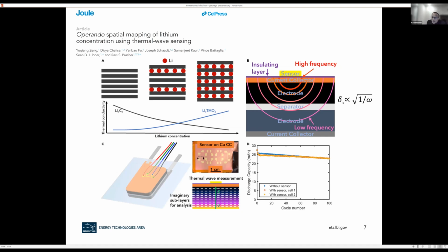And the thermal penetration depth, right? This is basic heat conduction. The thermal penetration depth of this thermal wave is inversely proportional to the square root of the frequency. So that means if I have a higher frequency, the wave is focused here. If I have a lower frequency, the wave penetrates deeper inside. So I can really probe the different layers, or what's happening as a function of thickness, right?